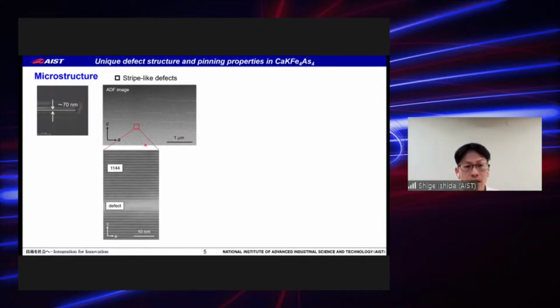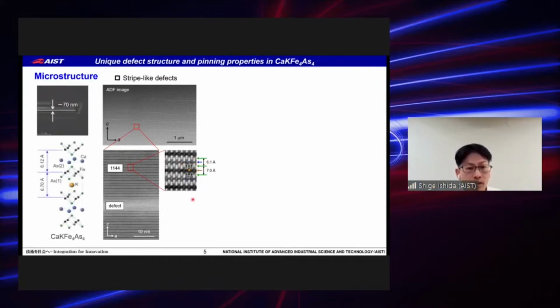This is a magnified view around one of the defects. The high resolution image of the matrix part reveals a bright zigzag corresponding to the iron arsenide layer, and relatively dark layers with different layer distances corresponding to calcium layer and potassium layer respectively, which are in good agreement with the crystal structure of calcium potassium 1144.